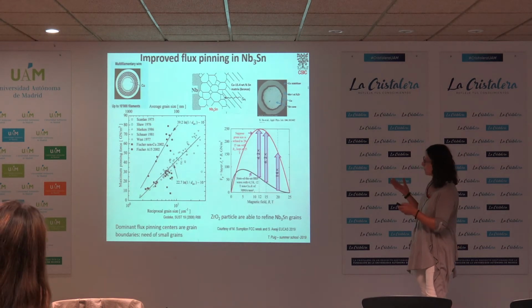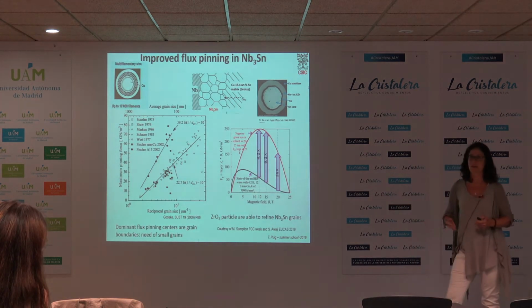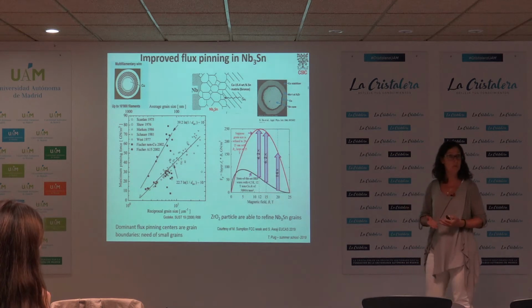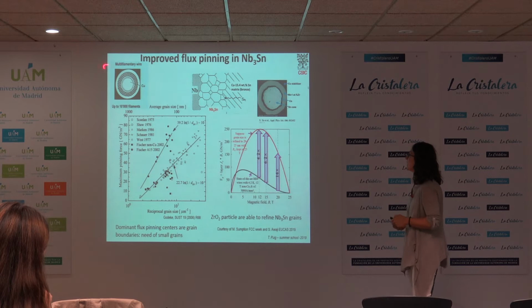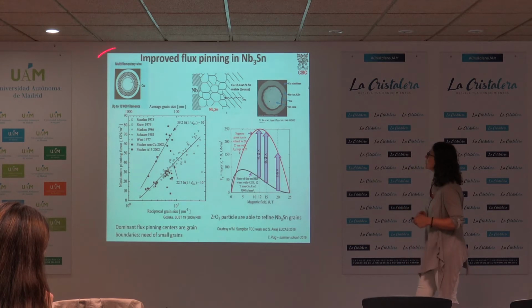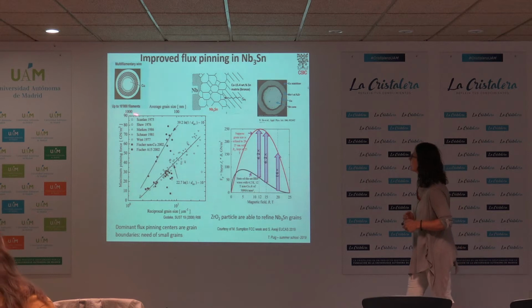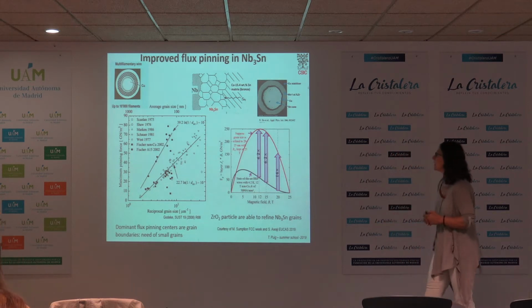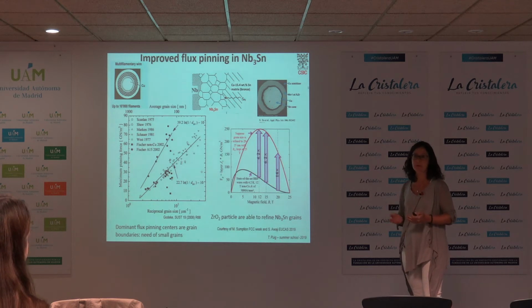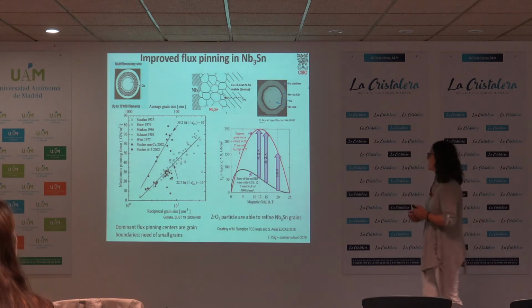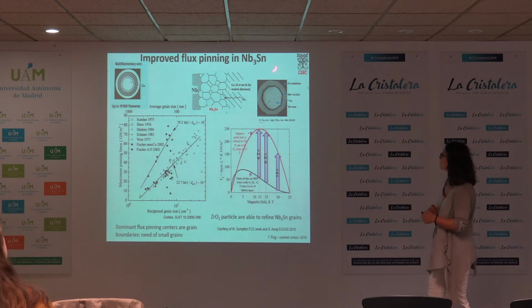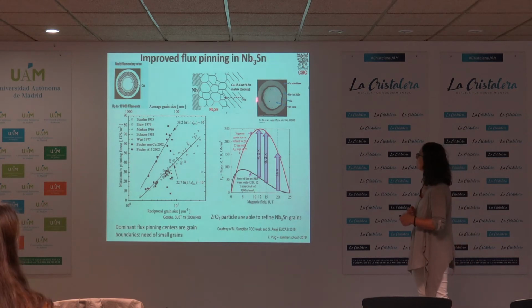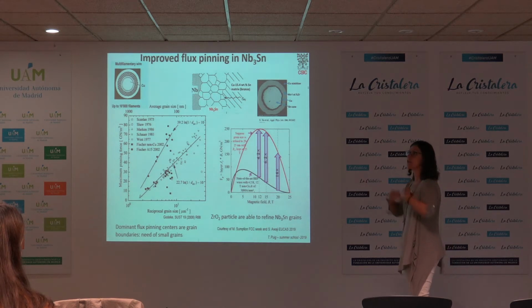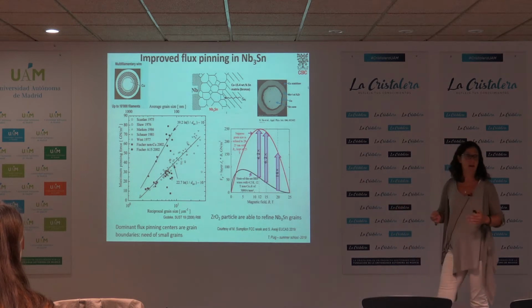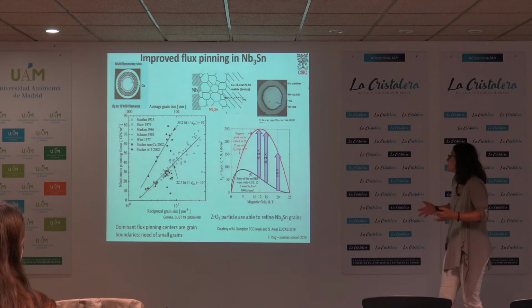And one can think, why is niobium-tin, which is already 50 years in the market, still a problem for applications? Why do we still want to improve this material? Mainly because the application is a multifilamentary wire, where we have maybe 10,000 filaments of niobium-tin, and still 50% of the material is not used as superconductor. To generate the niobium-tin, the tin core has to diffuse through a copper matrix into the niobium, and that is a complex method, a complex material science.